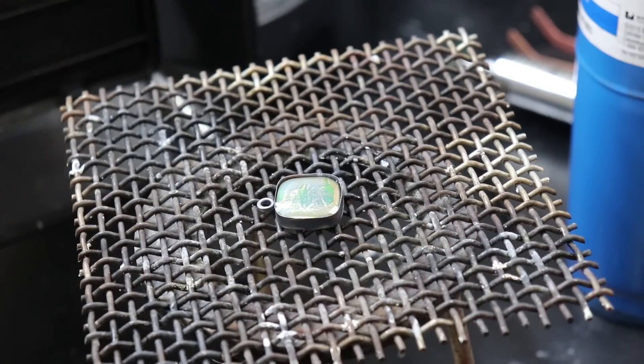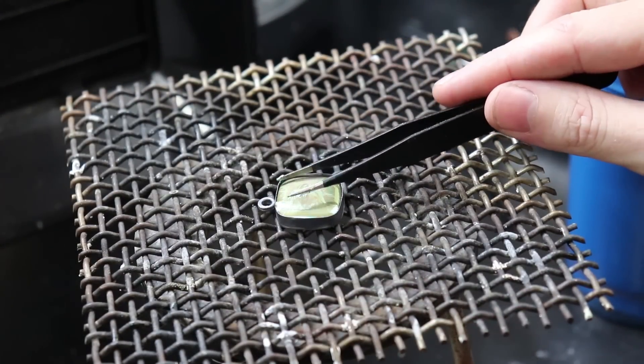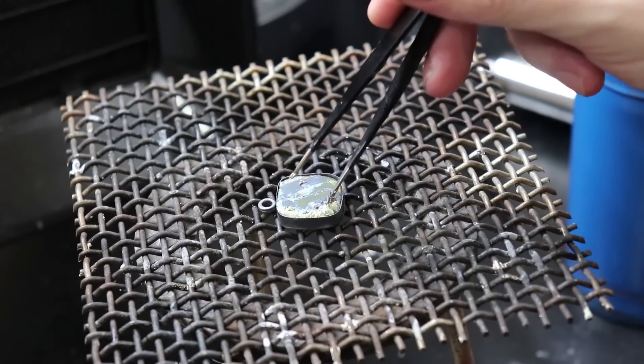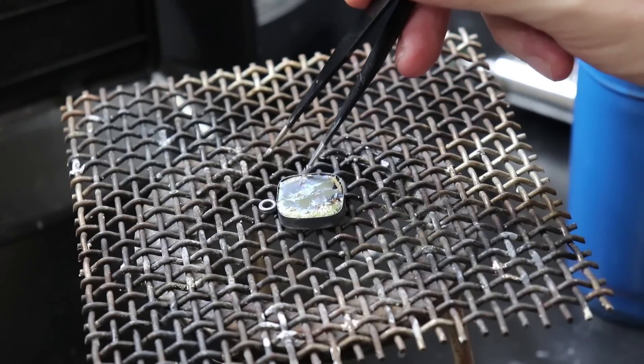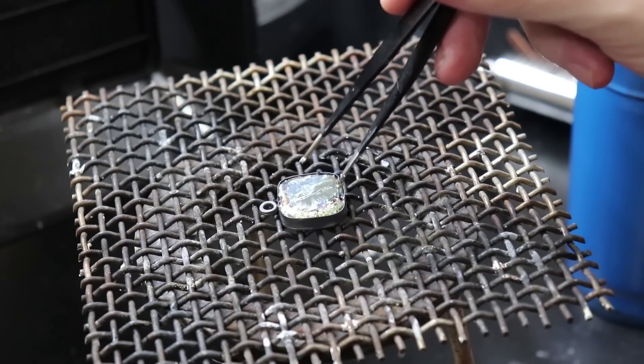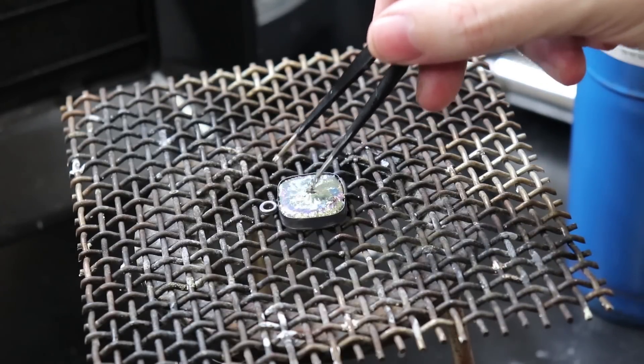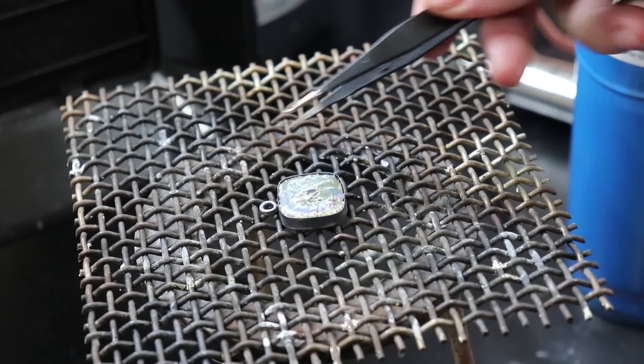To make this work you have to heat your piece until it becomes red hot. The repeated heating also made the patina I applied pretty much useless — the entire piece is now fire scaled, so I'll be taking that off after I get the bismuth to work properly. Now that it's all up to temperature I can pour the bismuth directly into it. I'll test it with my tweezers by putting them into the liquid bismuth and seeing if parts are starting to harden up, and once I feel there are enough hard parts I'll pour the rest of the liquid out. Be careful at this point because it's still extremely hot. This is a very temperature and time sensitive process — it takes a couple of tries to get it right.